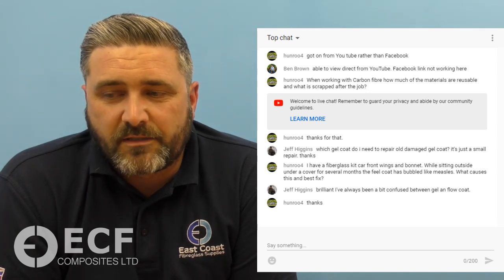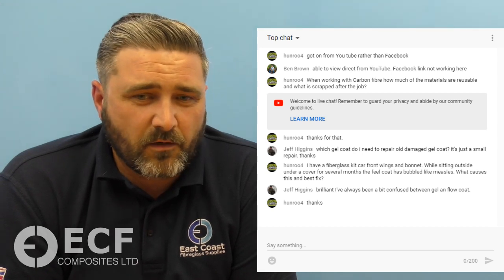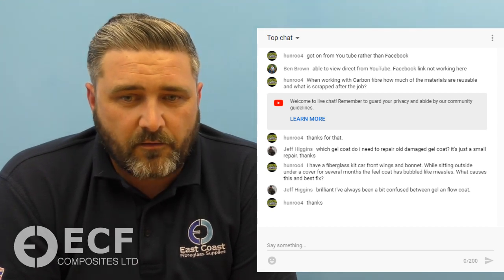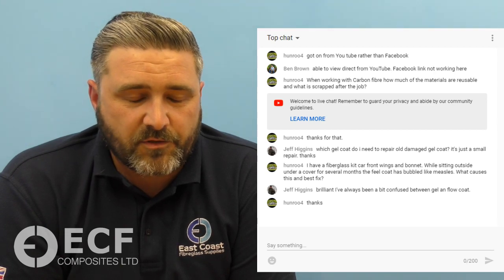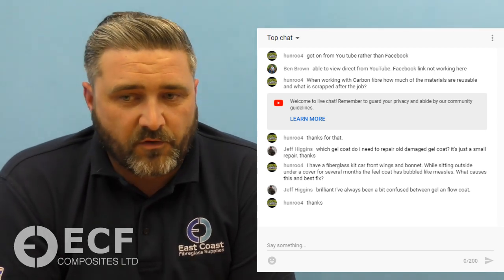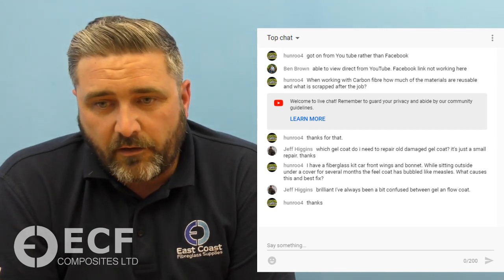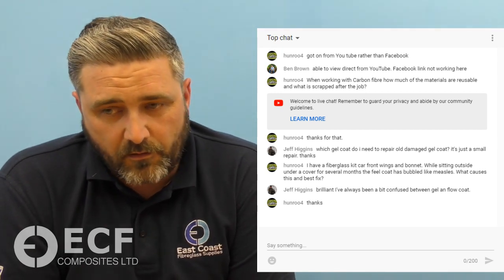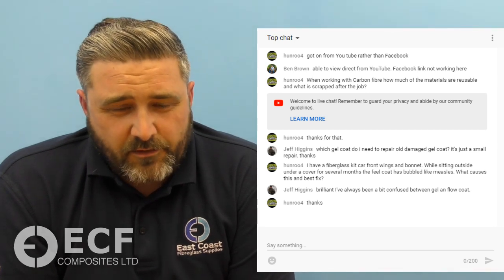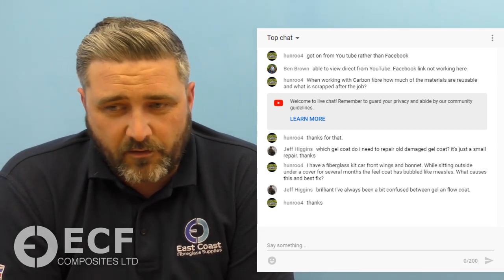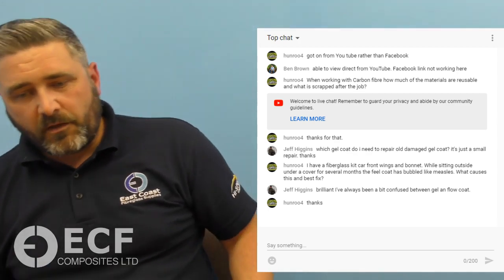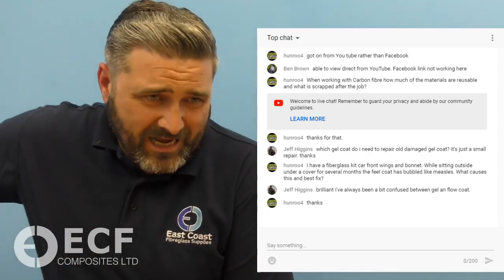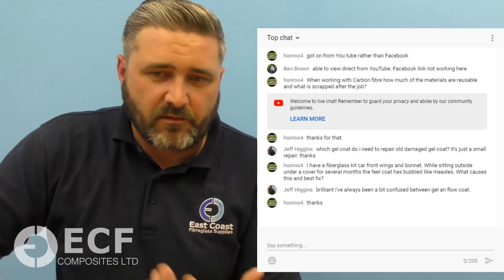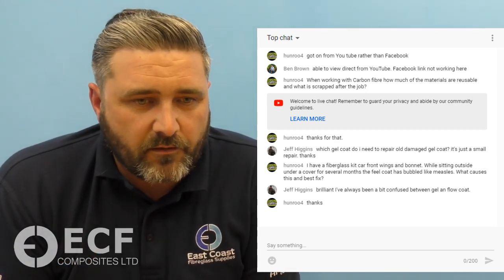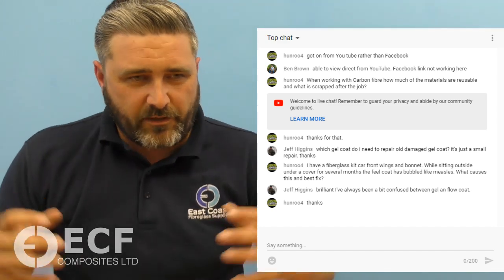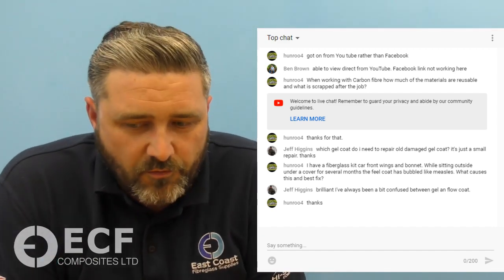The other common mistake for first time use is using it in the cold. A lot of people haven't got access to a decent temperature controlled workshop, so a lot of our first time users might just have a shed or a garage that isn't heated very well. It is a good idea to get some heat in there, even if it's just a fan heater. When I'm working in my garage, I just have a small fan heater at a distance. You don't want to create any hot spots because that will cause problems on your panel with shrinkage and distortion. So you just want to get a good ambient temperature around the room.